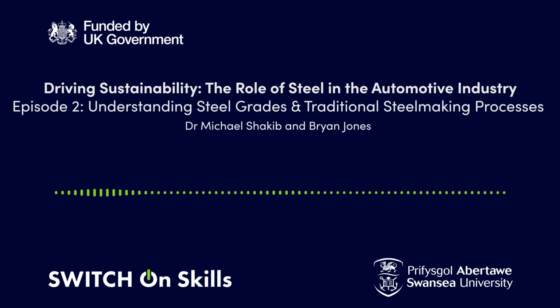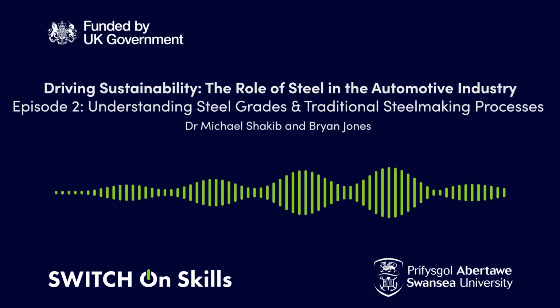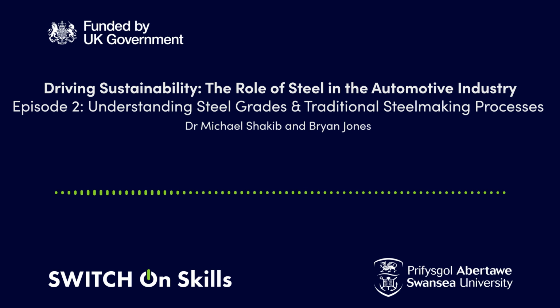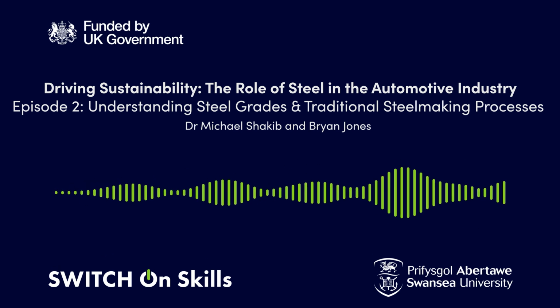So this is where you move on now to the secondary steel making process, which has particular significance in generating a product appropriate for, say, automotive applications. So you've got the RH (Ruhrstahl-Heraeus) process, which is a vacuum degassing process, which can reduce the carbon and nitrogen level down to 0.003% carbon and nitrogen. So that's suitable as an interstitial free steel, which is used in automotive assembly, where you've got particularly challenging applications in terms of formability.